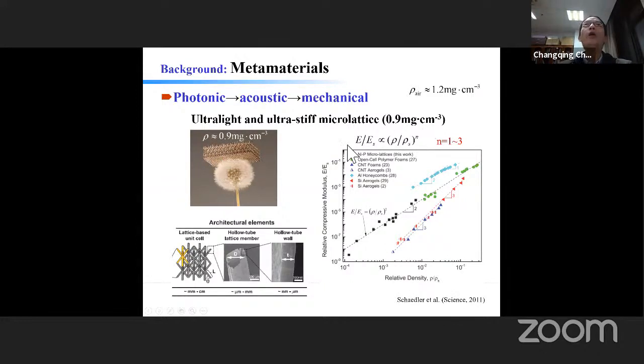Usually, we expect the relative modulus to have a power law relationship with the relative density, proportional to the relative density to the power n, usually n in the range between 1 and 3. Because the relative density here is less than 1, a big value of n indicates a soft material, because the modulus will be lower. So usually if n goes to 1, it's good, but if it goes to 3, it's not so good.